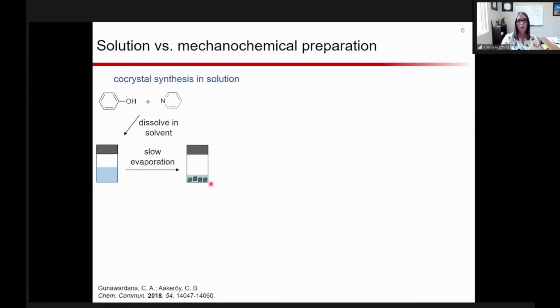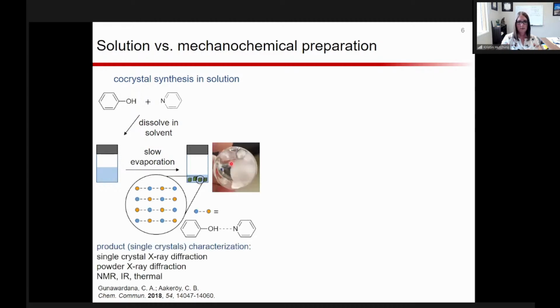And ideally, you will make co-crystals here. It might look something like this. This is just one of ours, a vial that we took a picture of in the lab. The crystals are a little bit small, but you can see them here, and then a little bit of the solution still left. Ideally in this process, you will actually get a co-crystal of the 2, meaning both components are present, instead of individual crystals of the 2 components separately. That's what I mean when I say you have to tune this a little bit, because sometimes you actually get crystals of molecule A and B independently, rather than getting them both in the same crystal. And so a little bit of tuning goes into that.